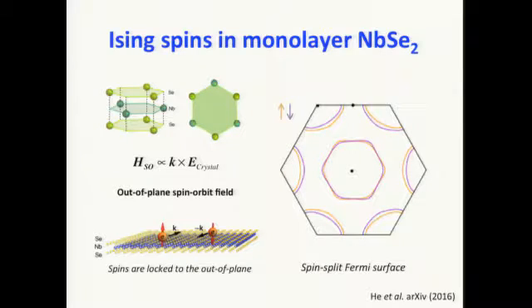Okay, and furthermore, we can actually figure out where the spin is pointing by looking at the crystal structure. The material has out-of-plane mirror symmetry, so the spin-orbit field can be written as the momentum of the carrier cross the crystal electric field. The crystal electric field has to be in plane because of the out-of-plane mirror symmetry. The momentum has to be in plane as well, so that means the spin-orbit field is only out of plane, only pointing up or pointing down.